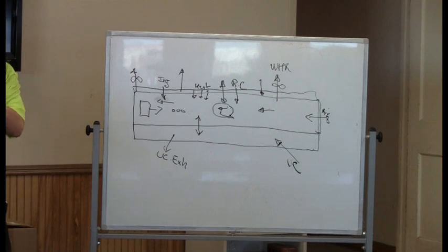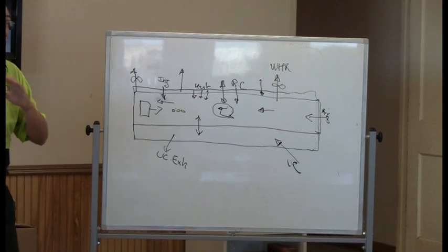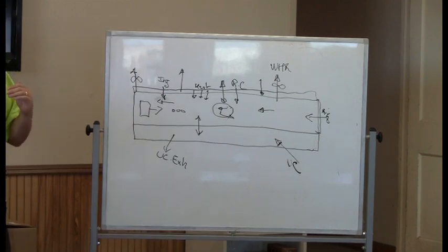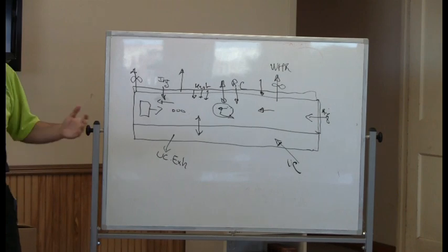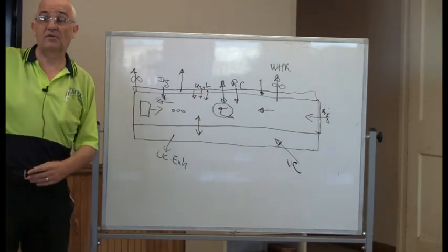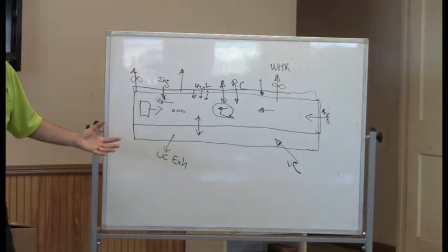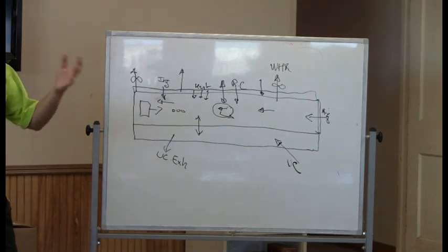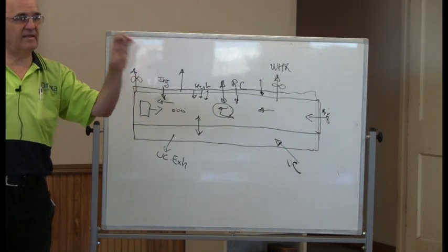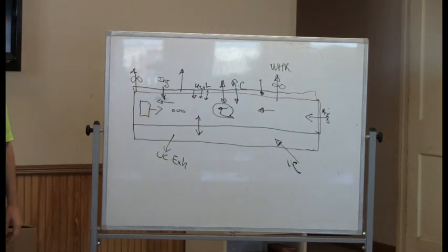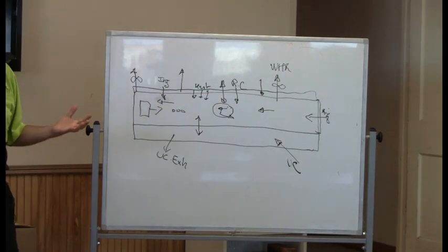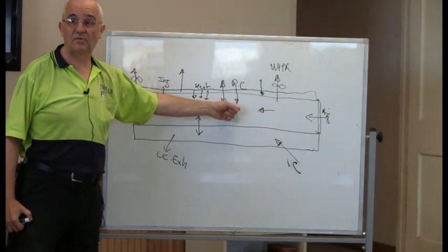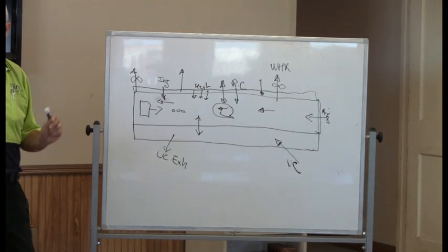When an engineering company designs a dryer and a kiln, most of the time we have a booster burner, because we know not all scenarios are capable of supplying the heat needed for the dryer by the kiln, especially when you have a light product in the kiln and a transition on your dryer with a heavy product. You are not going to be able to supply the energy, so you need the booster burner. But the booster burner is more efficient at delivering the heat specifically at that time, at that spot, than trying to steal it from the kiln and having all the burners doing much more work because, hey, I'm missing that energy in the tunnel. So as long as you guys are happy with that, it's good.